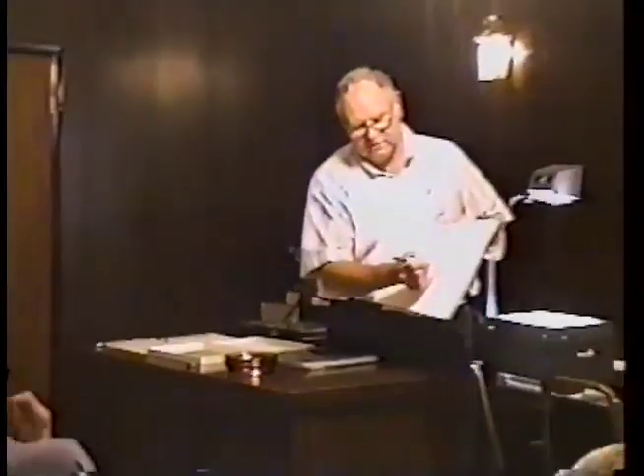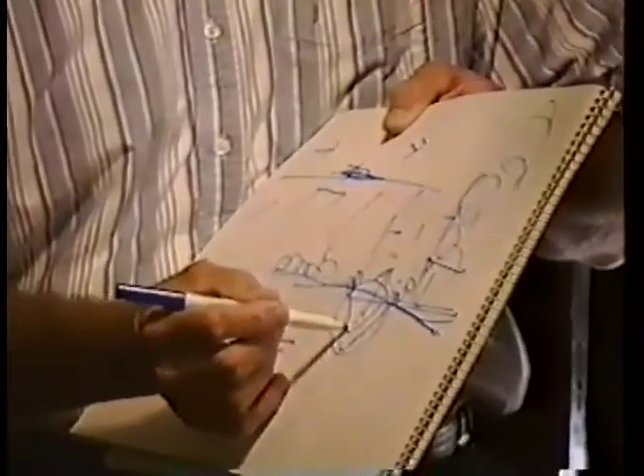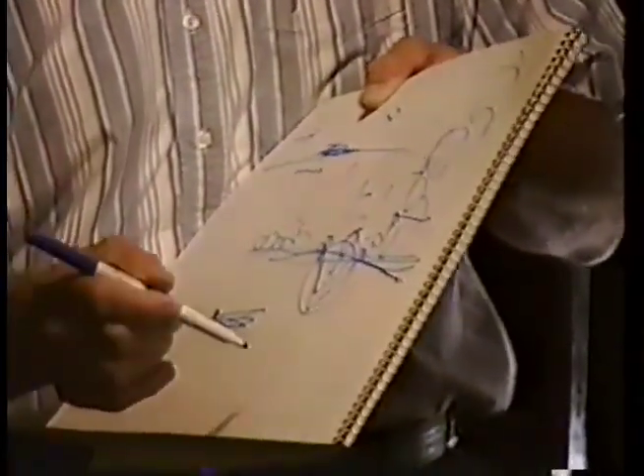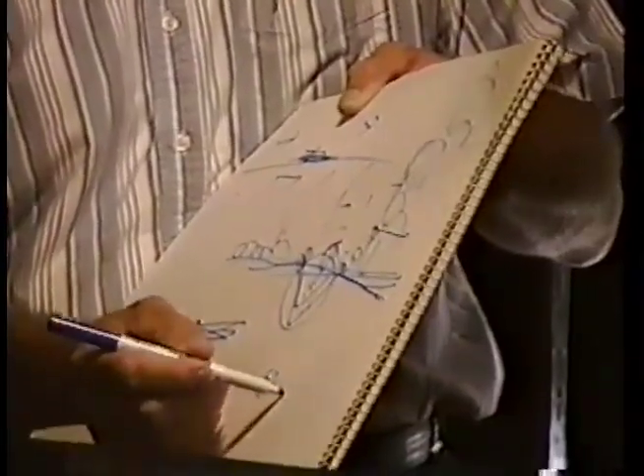When we blast that surface with fine grit, it tends to draw out of the pits moisture or solution from the honing process that's in those holes, and we're able to identify those pits. They'll show up as a dot, and the solution, through capillary reactions, shows up right on that surface. So we can go back and correct that right away. That's one of the major problems: the surface that you're trying to plate on has got to be prepared correctly, adequately enough.